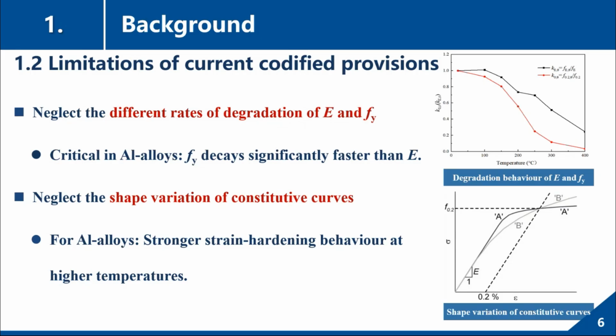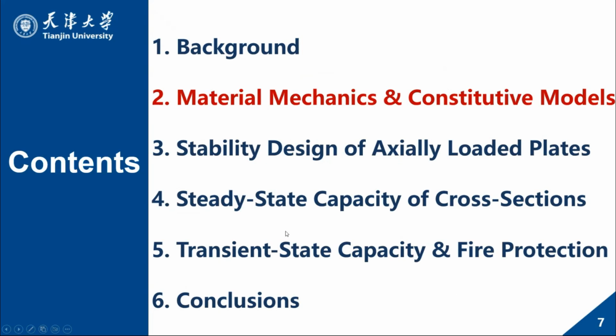The second point is that current codified methods neglect the shape variation of the constitutive curves of aluminum alloy. There is a stronger strain hardening behavior at higher temperatures, and this influences the high temperature behavior. So the codified method should consider this. So this is the background.